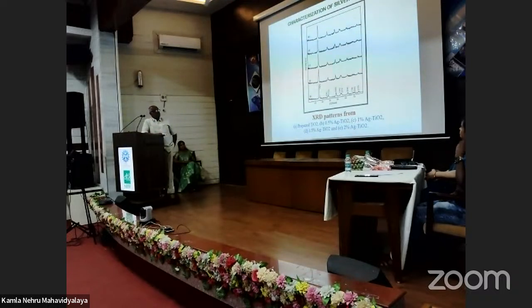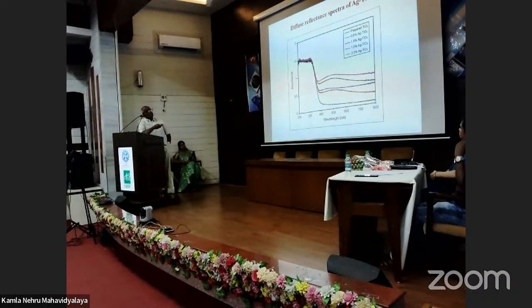So this is actually the external factor, and you can see 0.5% silver loaded TiO2, and 1%, 1.5 and 2%. You can see that 1% silver loaded TiO2 has the maximum absorption. So initially, whenever you prepare a catalyst, to find out whether it is solar active or not, you have to take a DRS spectrum and find out whether the absorption lies in the visible region or not. Then only can we go for solar active applications.